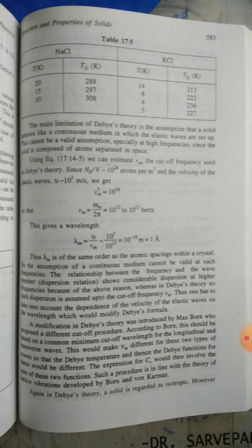The relationship between the frequency and the wave number, the dispersion relation, shows considerable dispersion at high frequency because of the above reasons, whereas in Debye theory no such dispersion is assumed up to the cutoff frequency νm. Thus, one has to take into account the dependence of the velocity of the elastic waves on the wavelength, which could modify the Debye formula.